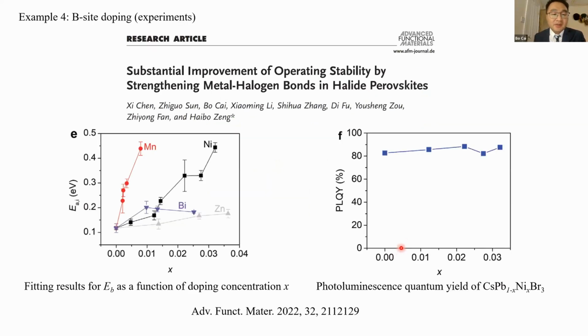The last example is actually the experimental version of the third example. My collaborator fabricated a series of B-site doped perovskites. The left figure shows the ion migration barriers versus doping concentration x. The barriers increase rapidly with doping concentration. Meanwhile, the PLQY is maintained at a relatively high level. Example 4 is in good agreement with our example 3.